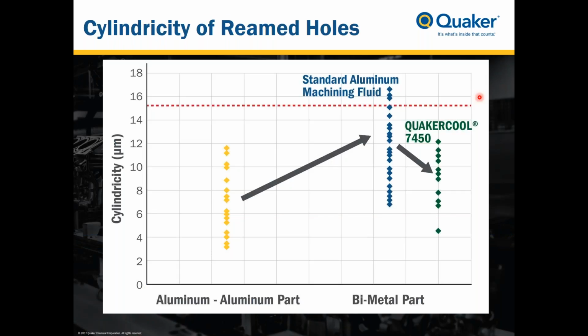What I'd like to do is just show the impact this fluid can have relative to the standard semi-synthetic that we used earlier in both cylindricity and in surface finish obtained. And what this graph shows is the cylindricity. It's basically the same graph as we showed earlier. Cylindricity is listed on the y-axis. The aluminum part using the standard aluminum machining fluid performs well. The bi-metal part using the standard aluminum machining fluid shows the degradation in the cylindricity measured.